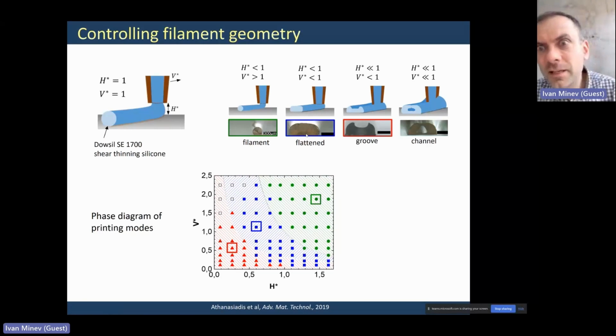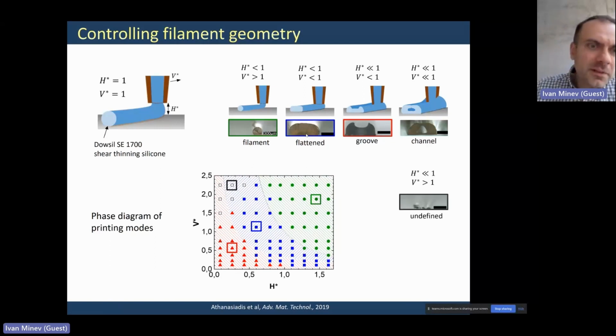And if we go even slower and closer to the substrate, a groove starts to form in the extruded filament. We also observe some regimes in which the walls of this groove can collapse, forming a microfluidic channel, a kind of standalone microfluidic channel. We explored the phase space and found that by tuning these two parameters, V and H, we can decide which of these structures we produce. One of the materials that worked very well with this concept was this shear thinning silicone, Dowsil SE 1700. Other hydrogel materials were also able to produce similar structures.